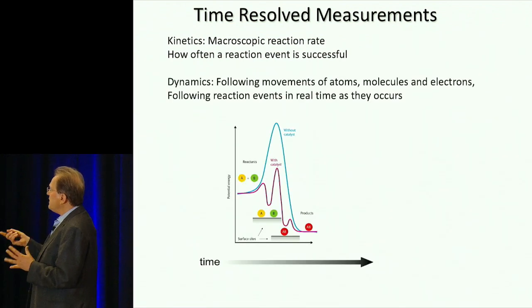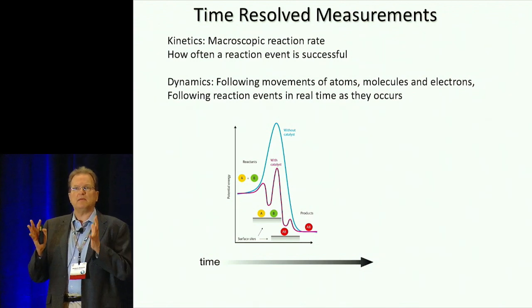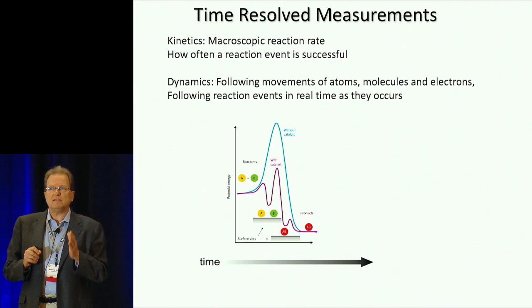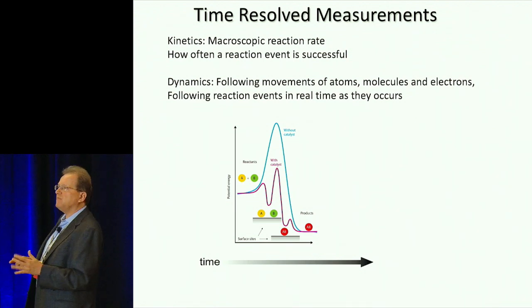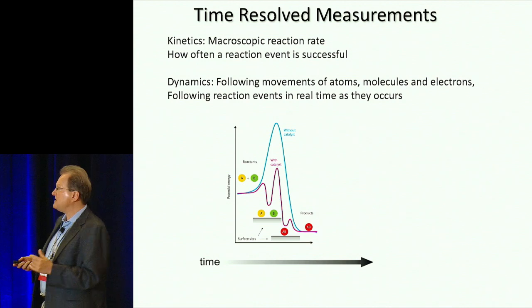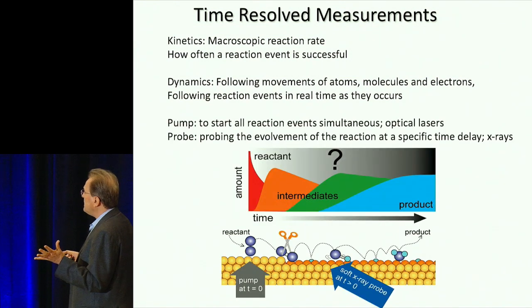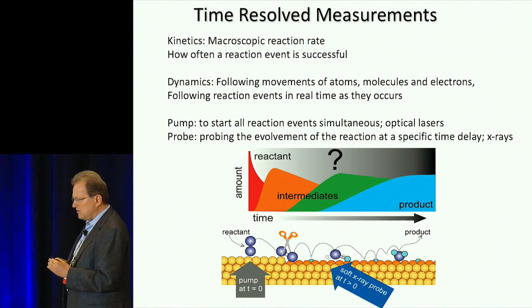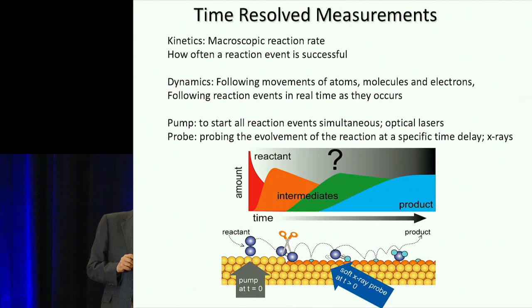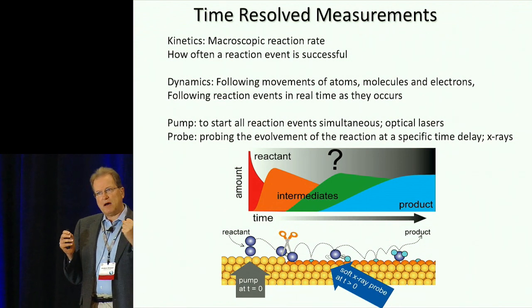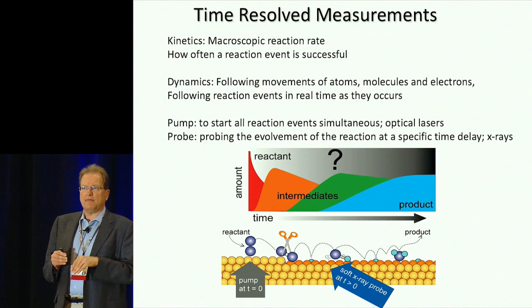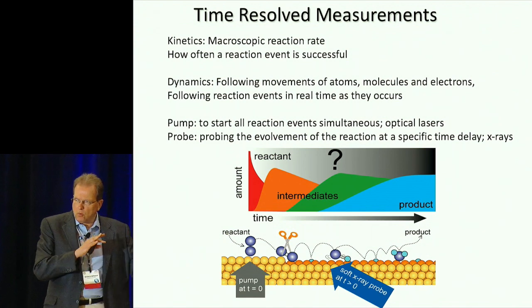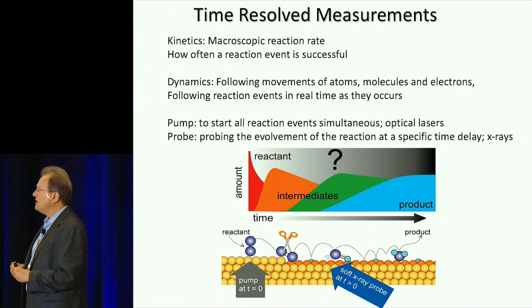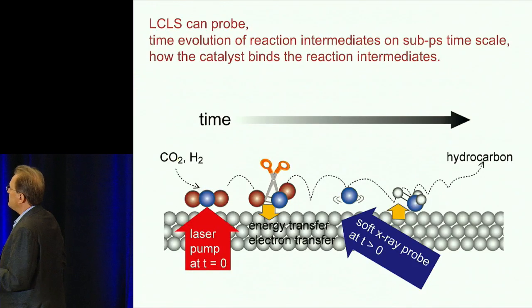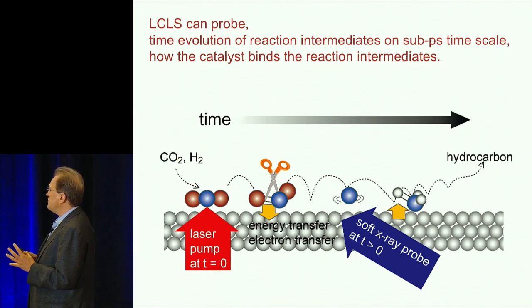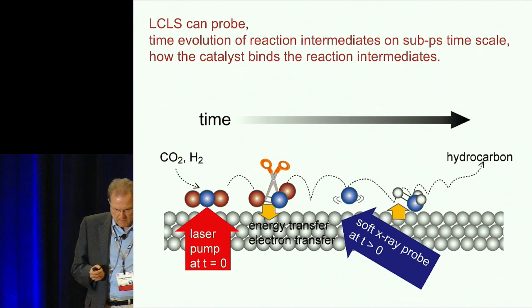So in order to do that, you really need to start all the reaction events to happen at the same time. You need to pump the system to really stimulate it, and then you can follow it. And that's what we call, instead of kinetics, dynamics. We do dynamic studies. And so what we are thinking here is that we simply have molecules on the surface, we pump it with an optical laser, we put in a lot of energy there. Actually, it's more a pumping of the electronic system in the substrate that couples to the molecules on the surface, and then all of them get kinetic energies at the same time, and they can start to react, so to speak. So we want to now look at that particular CO2 reduction, and the interesting step here is CO reduction.